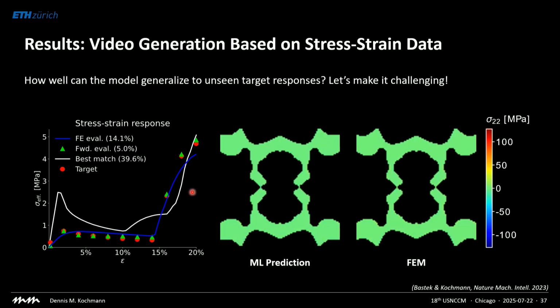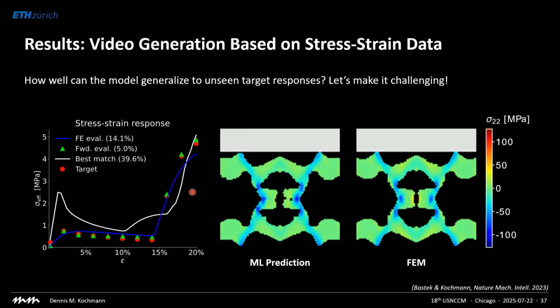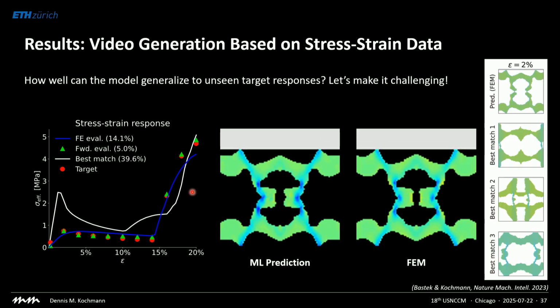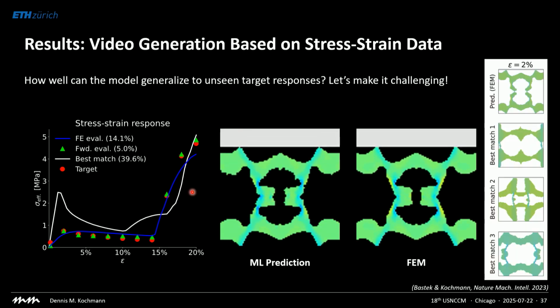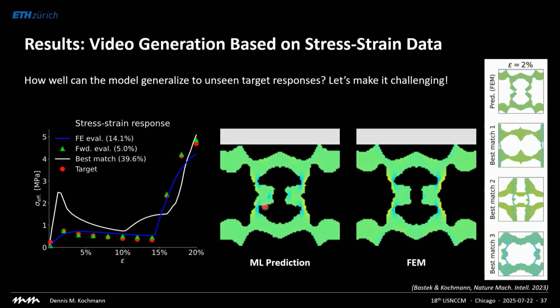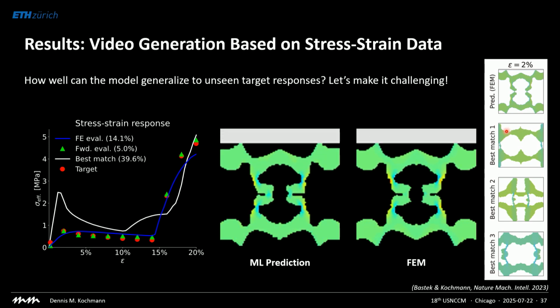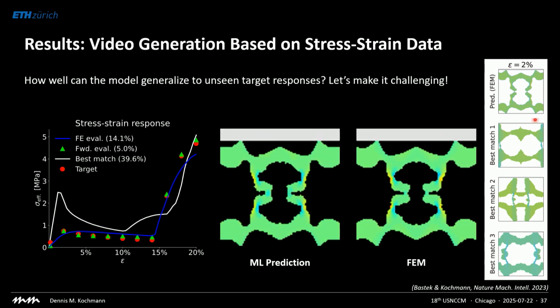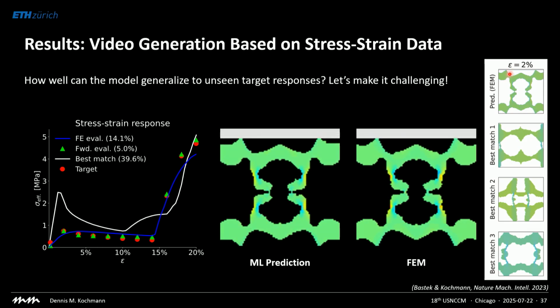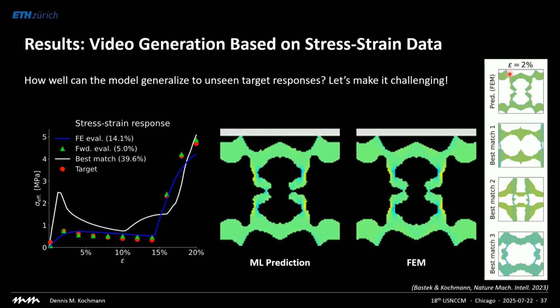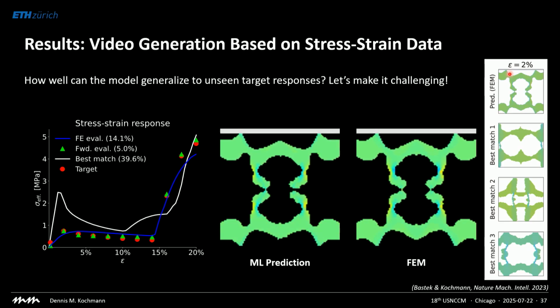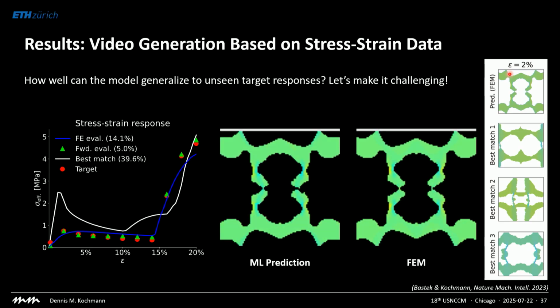We didn't do this just for one curve. We did this for thousands of curves and also reported the average errors and maxima. And what you notice is that this really generates interesting structures. In this case, for example, this is what the 3 best matches in the training data set look like. This up here is the structure we generate. So it really does not just interpolate between 2 nearby structures. It generates something new that was not contained in the training set without intuition or experience.